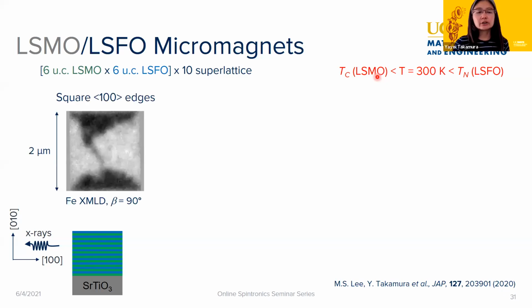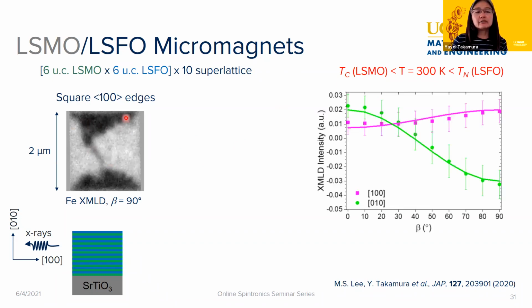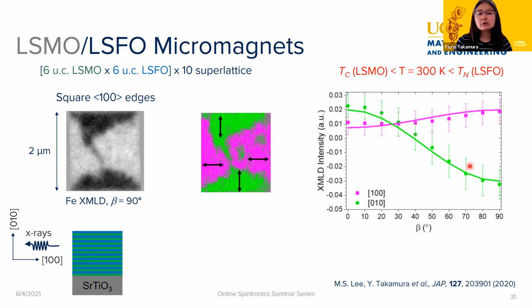And so then we took a look at the images. This is one image that we have from this. And now you can see that we have a much simpler domain pattern than we had before when we were just looking at one thin film, basically only having 2 types of domains. So we don't get the 4 domain binning, we only get 2 types of domains. And again, we can map these out. What was black we've binned as green, and then the white shows up as pink. And then you can see that we have these gray domains at the borders, which we can't really bin. Those are the domain walls themselves.